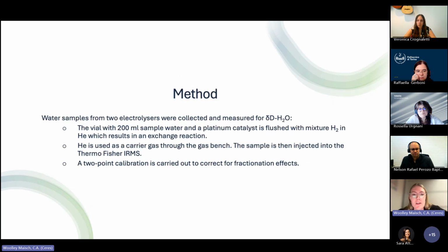And then we also measured the delta D of H2O, so the deuterium content of water. This is also a similar method. Basically, there's a pre-concentration step where we fill a vial with just 200 milliliters of water. And then after some steps, it's also carried to a Thermo Fisher IRMS.